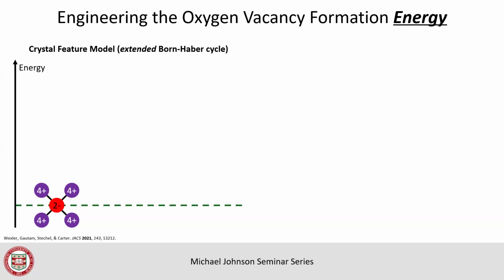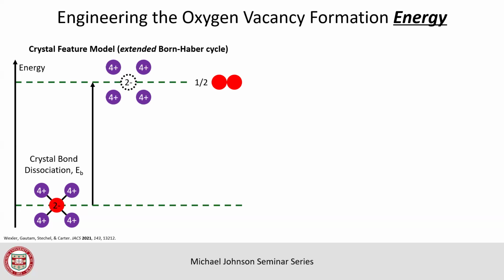If you have some set of cations or positively charged metals, they've lost their electrons, and those electrons have gone to an oxygen because oxygen likes to get electrons. You can imagine the process of knocking an atom out of the lattice as follows. First step is the energy required to pull out a neutral oxygen atom and leave its electrons behind. Okay? Details of that, maybe not worth emphasizing too much, but basically one step of this is thinking about if you were to just cut the bonds and let the electrons go back to the metals, right? What would be the energy released when you cut the bonds? If you pull a rubber band and you cut it, it snaps back. What was that energy stored between the positively charged cations and the oxygen that's there? There's this first energy. So you can imagine energy goes up. You need to supply energy to make this happen.